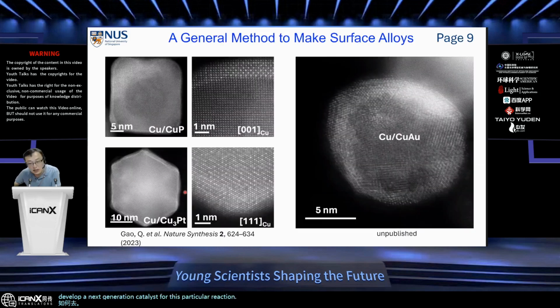So this is what we have achieved: we use a simple galvanic replacement method. Basically you make a copper nanoparticle first, then you put them into a solution that contains precious metal cations. Then the galvanic replacement reaction takes place. And then at a relatively low temperature, you can see that we can form an intermetallic phase only on top of a few layer surface. So this will give you the intermetallic phase that you want to break the linear scaling relationship for the reaction. At the same time, you don't waste too much precious metal inside the material.